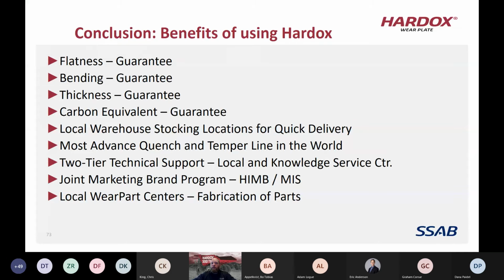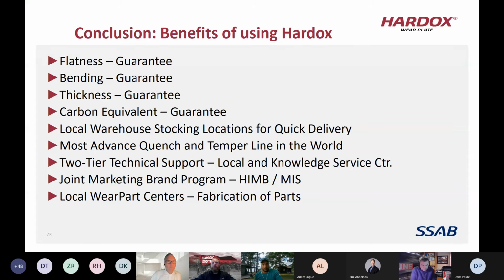So the big conclusions for Hardox: we have flatness guarantees, bending guarantees, and thickness guarantees, and our flatness and thickness guarantees are better than ASTM standards. They're better than EN standards. And we also have a carbon equivalent guarantee, so that guarantees you're going to get good welding results every time. And our plates are very consistent from one day to the next, or one month to the next, and year over year. We also have local warehouse stocks.